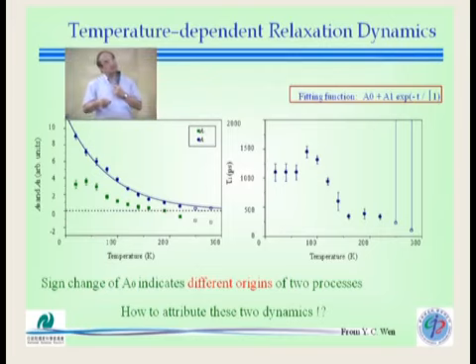Right. And the data indicate the relatively slow electrons respond differently. There's a crossover at about the same temperature. The phase response at 100 Kelvin, then the relaxation time is different. This is the electron response to the optical energy. There's a very fast response, and then there's a sudden change. So all this indicates this 100 Kelvin is fundamentally very important to the distortion, and gives you a lot of interesting electronic change, and that is also related to the spin structure of the system.